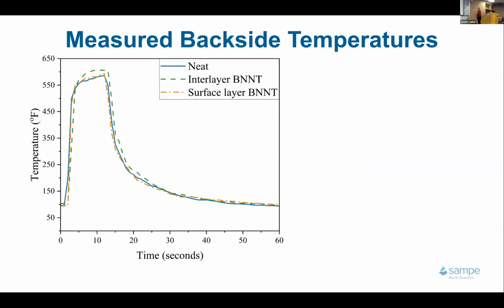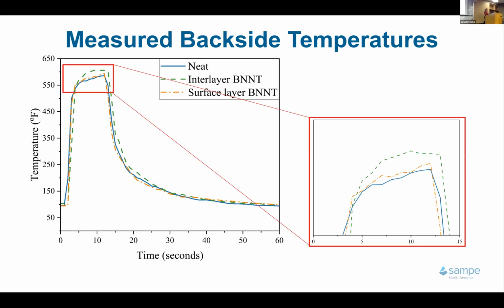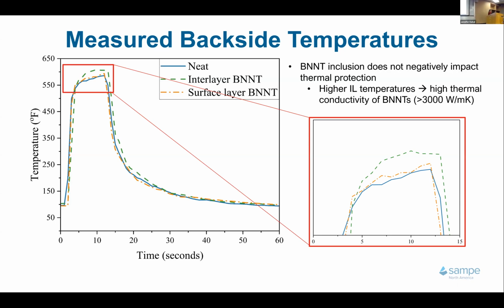So we again have the measured backside temperatures between the neat, the interlayer, and the surface layer. Very different from our last finding. So this is heat and pressure, not quite as hot as the propane, but under pressure. The pressures can cause some kind of wacky things to happen. Zoomed in, we can see that the interlayer actually shows the highest temperature and the neat shows the lowest temperature. Not exactly what we want, but it's interesting nonetheless to further study. So it basically shows it doesn't negatively affect it, but it doesn't really help anything when we have the high pressures added to the heat.